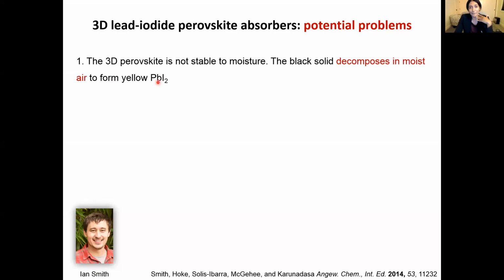So this means that if you're trying to make perovskite devices in large scale, all of your manipulations have to be done under strictly water-free conditions, which is quite hard to do, which will really increase manufacture cost. And of course, the material will have to be rigorously encapsulated as well. So we wanted to engineer moisture resistance into the material, not as a layer you deposit on top of the material, but as something that's inherent to the material.